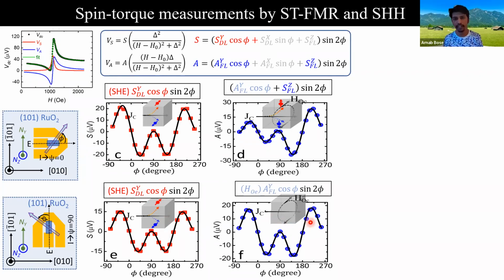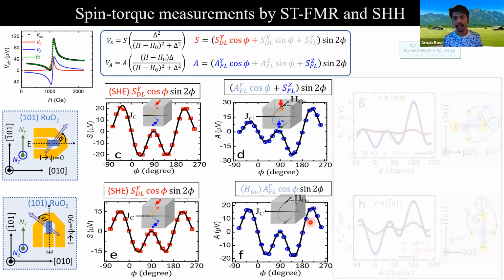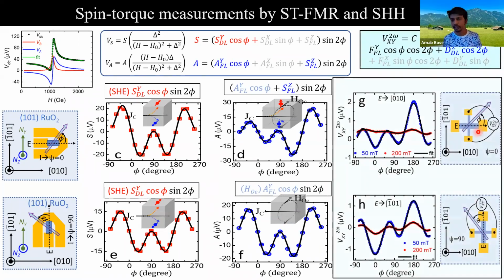We also want to verify this by doing another experimental technique, which is an independent study, that is a second harmonic Hall measurement. Just to remind you, for this, we pattern a Hall bar as shown here and measure the second harmonic Hall voltage by rotating the in-plane magnetic field. This is a typical second harmonic Hall voltage spectrum that you see. The first thing that we notice is the clear angular difference in the second harmonic Hall voltage when we run current along psi equal to 0 and psi equal to 90 as shown here. The difference is due to this extra term.